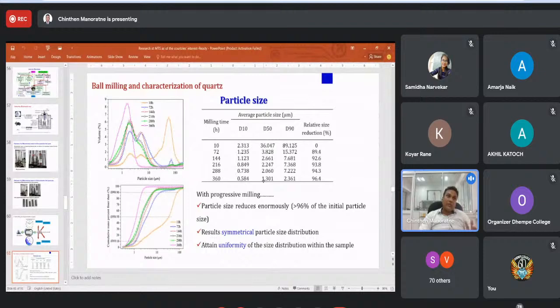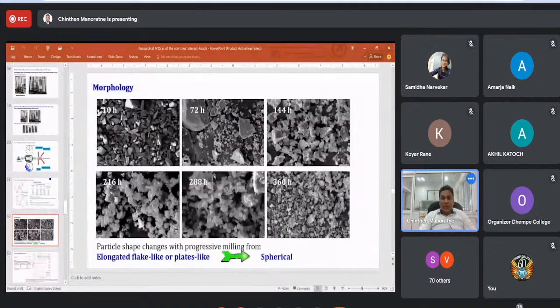And interestingly, we have observed nano quartz in this study. So that is one of the good findings that shows that this technique can be used for other minerals as a way of producing nano particles. Now you can see this homogenizing of distribution at 360. And progressively, we have reached 96% particle size reduction and symmetrical, spherical particles, and uniformity of the size distribution within the sample. Now you can see these corresponding SEM images at each time interval. Now you can see that at 360, we have spherical particles that are very uniformly distributed, and you can see nanoparticles as well. The raw quartz is elongated, I mean, there is no specific shape.